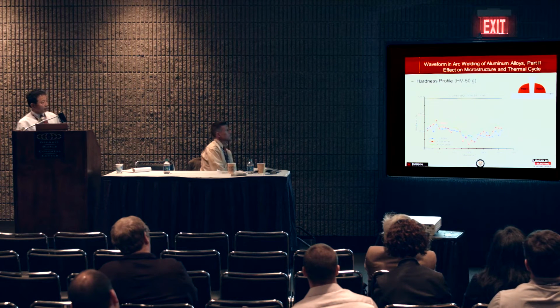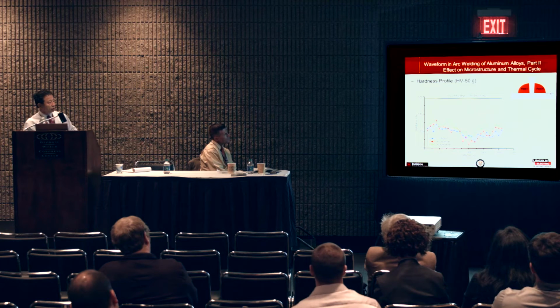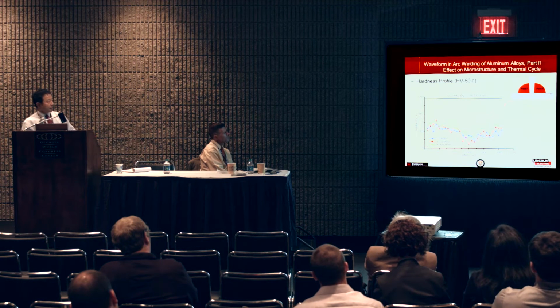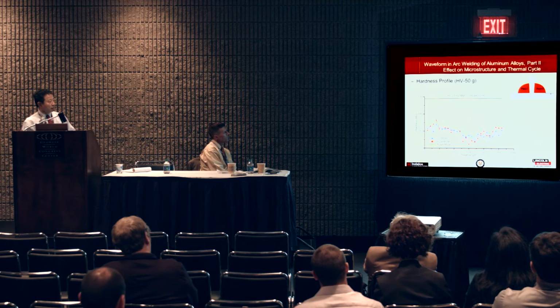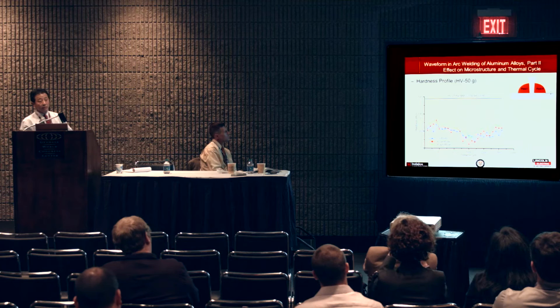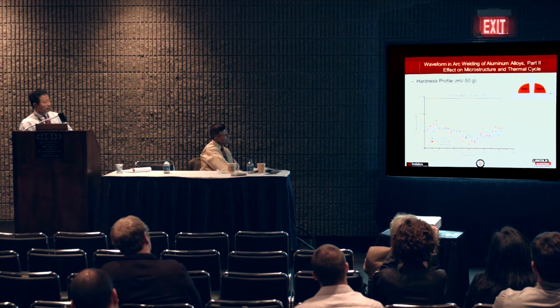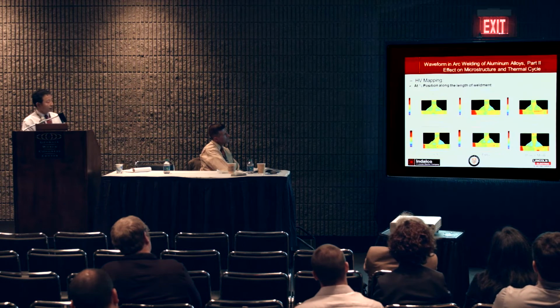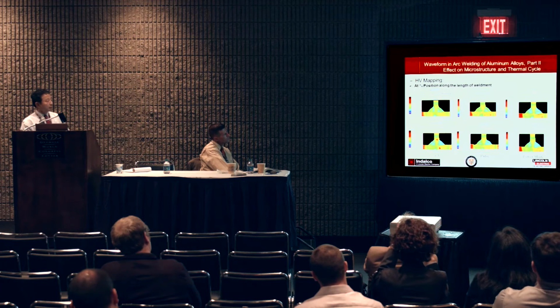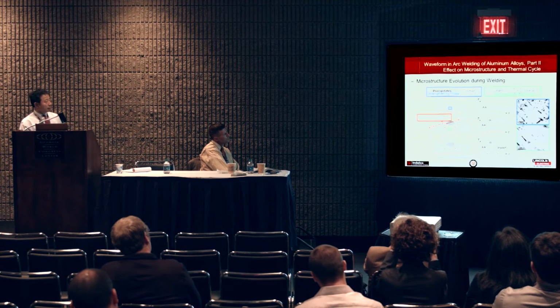And I also did a line hardness scan 200 microns below the top of my plate, and just to give you one example, it also shows that I got the best performance, the least softening in my heat affected zone relative to my base metal. Very, very good agreement with the hardness mapping results.